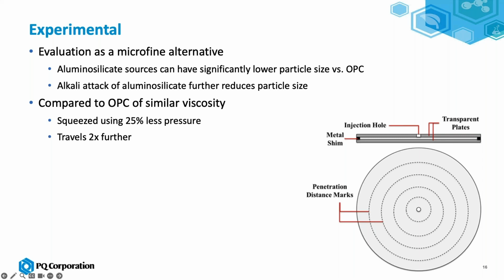If you look at most aluminum silicate sources, fly ashes, it'd be half the size of a typical Portland cement. And as it is mixed into the alkali, the silicate solution, it goes to a smaller particle size as it dissolves. Next slide.